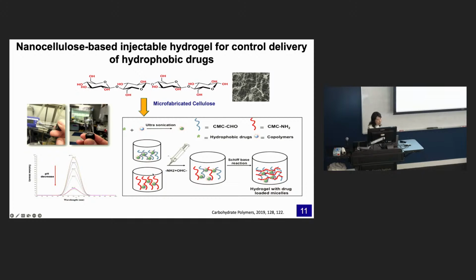Also, for another copolymer we used, the outside of the micelle structure is hydrophilic, so it can be put in our cellulose solution. And the inside core is hydrophobic, so we can encapsulate hydrophobic drugs inside. Then we can form a double layer to achieve slow, controlled and pH-sensitive release of the hydrophobic drugs, and also an injectable hydrogel based on cellulose.